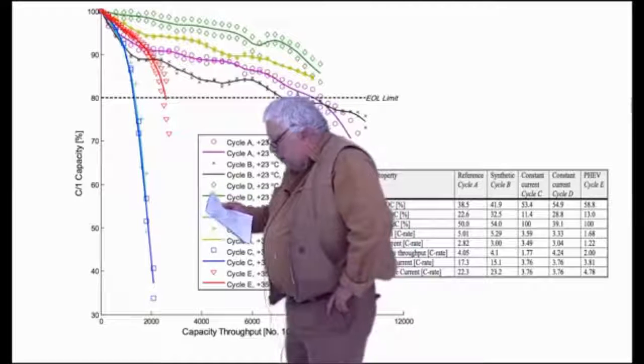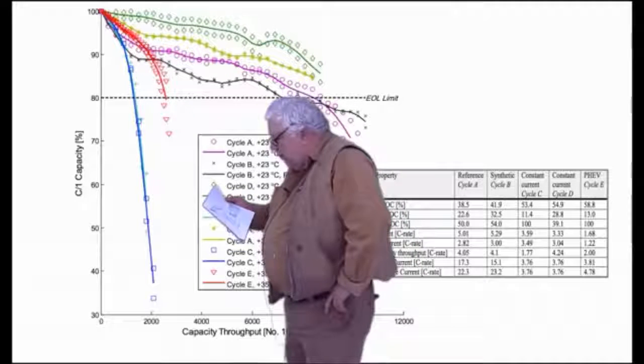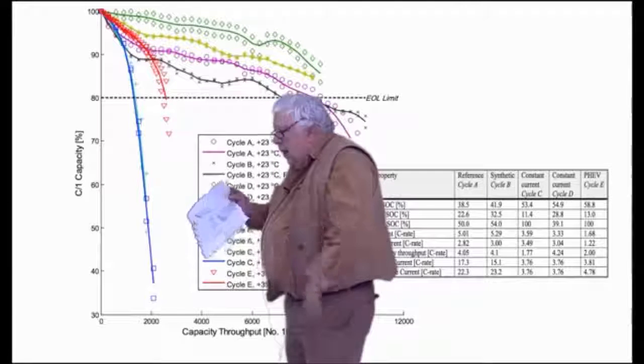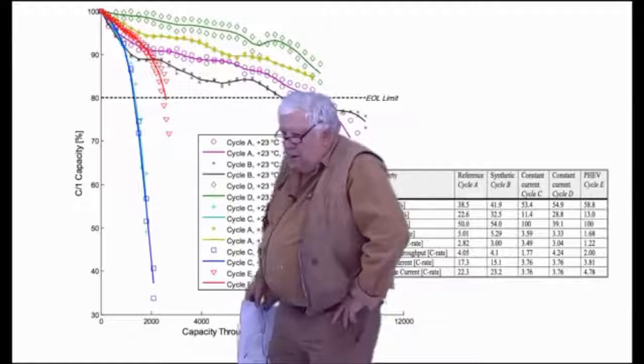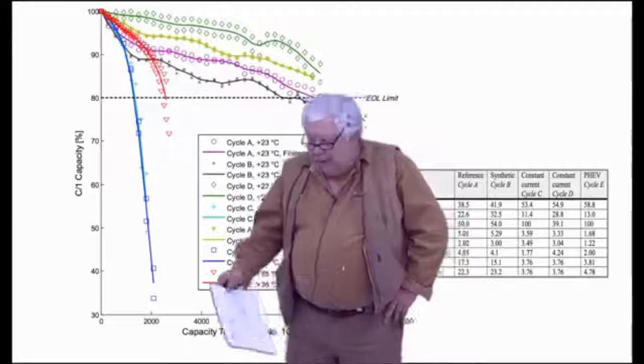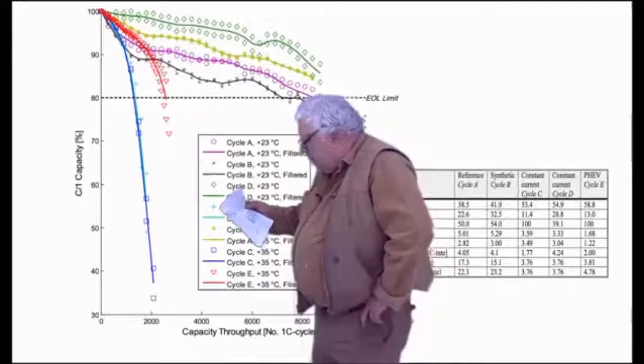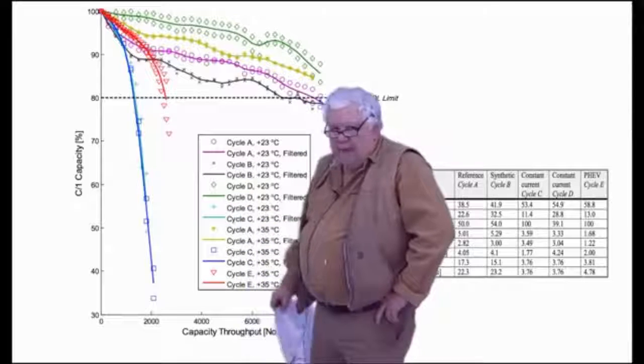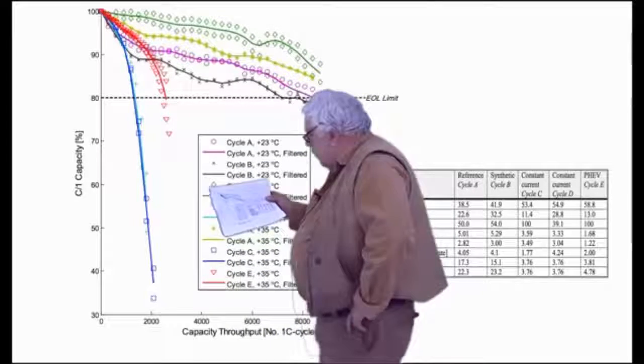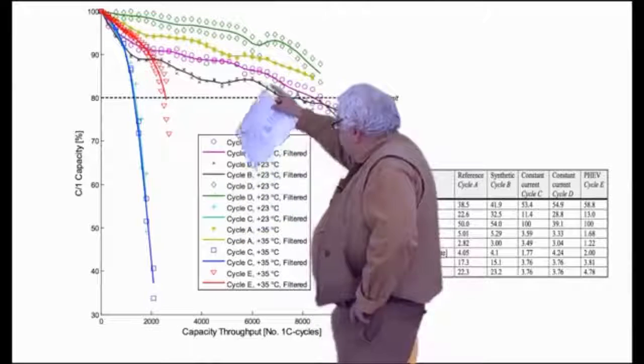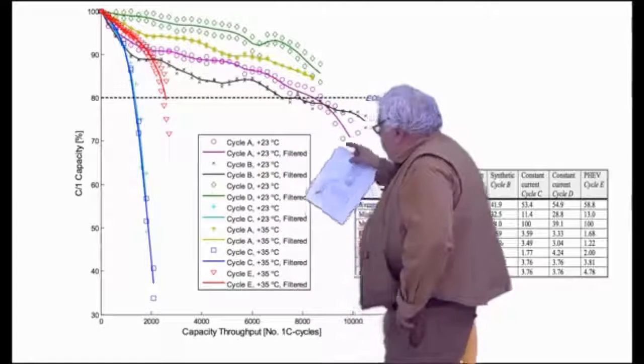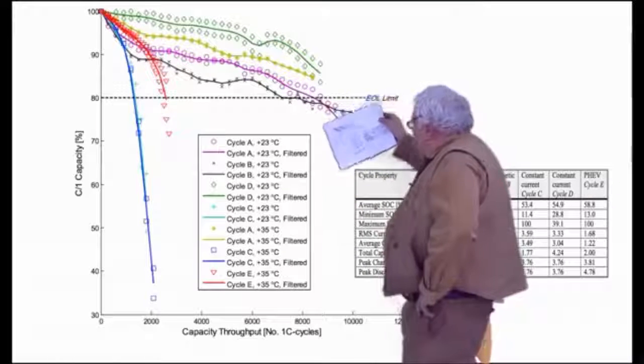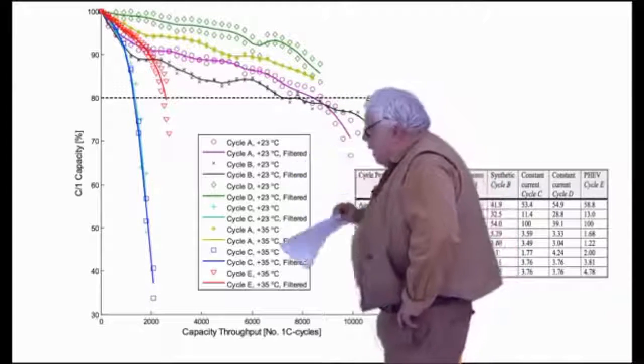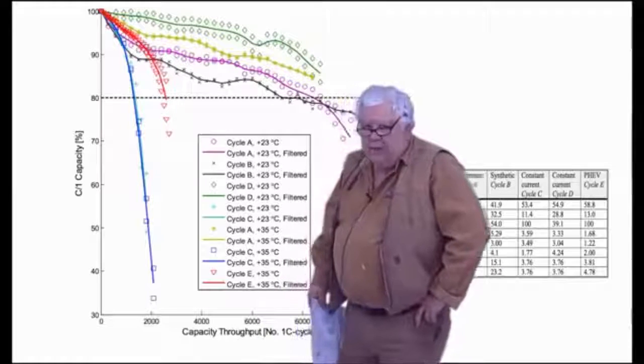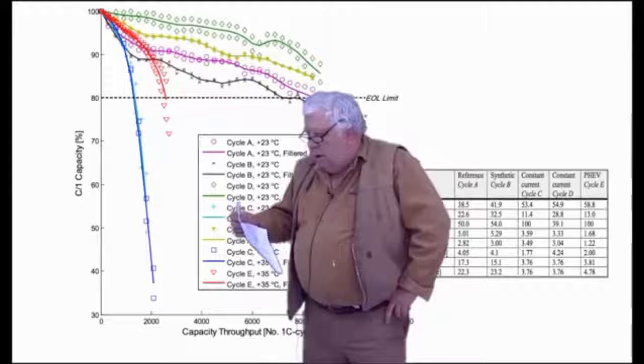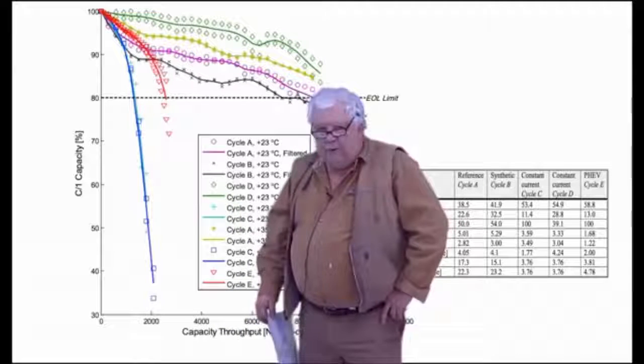This young man's student's work I find much more persuasive because of the number of cycles, the very careful climate control of the 35-degree test, and at every step on cycle A, the real driving cycle, you can see a clear differentiation between the green and the purple, with the purple failing first and the green never really quite reaching 80% during the test. It never did get down to 80% capacity on any of his interim RPTs, reference power tests.